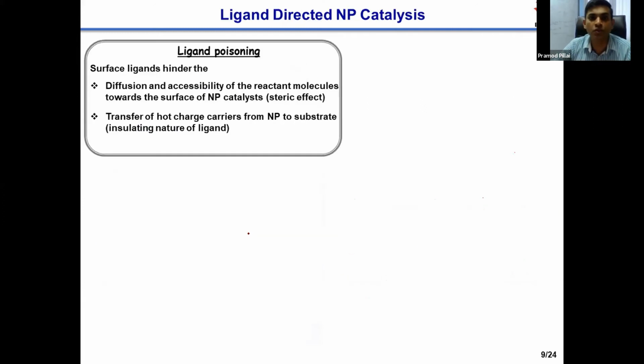The second important challenge with nanoparticle catalysis is the surface ligands. As we all know, catalysis is a surface phenomenon. You need the surface of the catalyst exposed to the reactants. Then only the reaction will happen. And this is where the surface ligands can play an adverse role. For example, they can sterically hinder the approach of reactants from the solution to the surface of the nanoparticle catalyst. The second thing is, most of the ligands that people use are insulating in nature because they are organic molecules generally, and that too non-aromatic organic molecules. So they are insulators, and they can hinder the transfer of electrons from the nanoparticle to the reactants. So this is known as ligand poisoning in the area of nanoparticles.